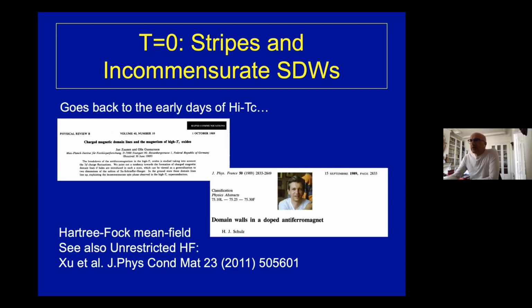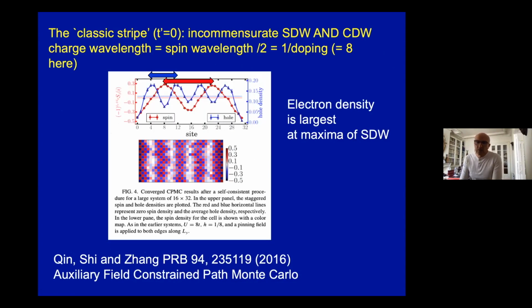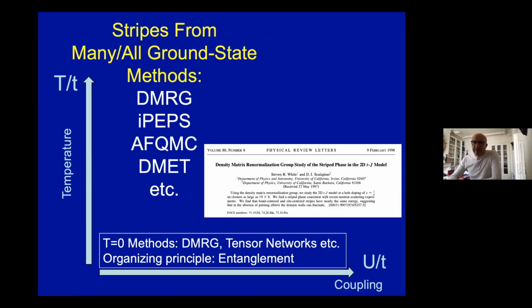And of course, since then, a number of methods have shown that at low doping in the strong coupling regime, there is the iconic picture of a stripe being formed, namely a linearly polarized spin density wave, which you see here in red, and holes living preferably near the nodes of the spin density wave, hence with a spin wavelength which is twice that of the charge density wavelength. So this has been confirmed by a very large variety of methods: DMRG, iPEPS, auxiliary field Monte Carlo, DMET, and so on.